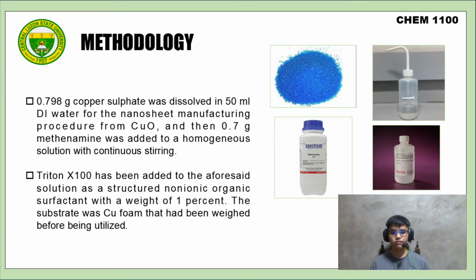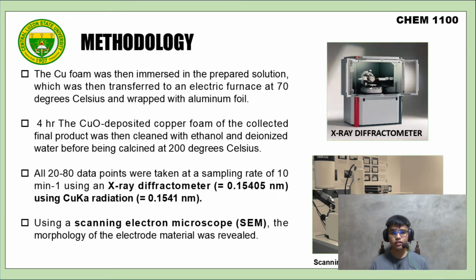0.798 grams of copper sulfate was dissolved in 50 ml deionized water for the copper oxide nanosheet manufacturing procedure, and then 0.7 grams of methenamine was added to form a homogeneous solution with continuous stirring. Triton X-100 was added to the aforesaid solution as a structure-directing non-ionic organic surfactant at 1% weight. The substrate was copper foam that had been weighed before being utilized. The copper foam was then immersed in the prepared solution,